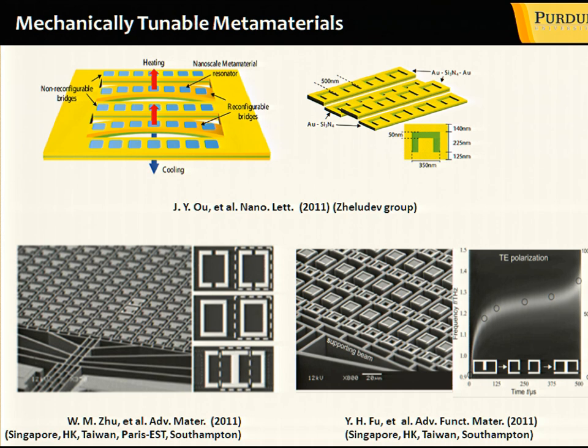And below you could see two other structures, which are basically micro-machines. They are magnetic metamaterials, which enable magnetic response in the terahertz spectral range. They use these usual split-ring resonators. What you could do is either open up the split ring resonator structure or close it up. And when you do so, of course, the magnetic response changes dramatically. In this particular case, it can go from negative to positive. Or you could have two layers of split ring resonators, as shown here, and just move one with respect to another. And in this case, they again show this switching capability for terahertz magnetic response.